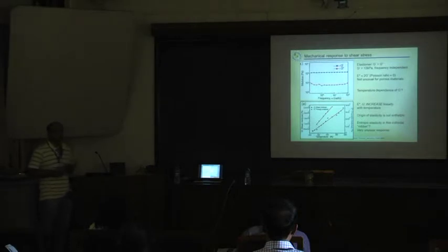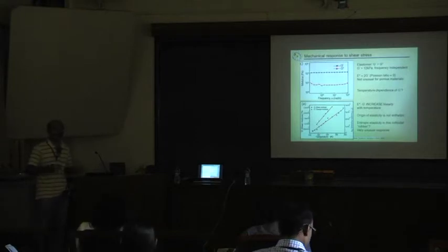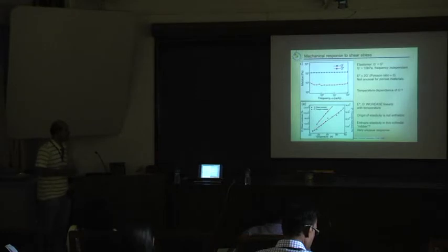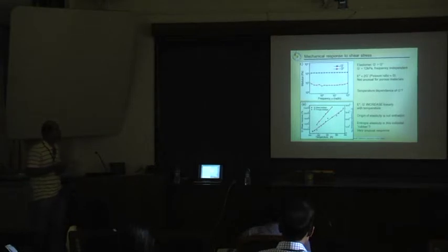Now that's very unusual because for most inorganic materials, or if you take a bunch of glassy particles and bond them together, you would expect a decrease in modulus as you go to higher temperatures. What we see is essentially a linear increase with temperature. That suggests that the origin of the elasticity that we are seeing in these materials is probably not enthalpic, and it's probably entropic, like you would see in rubbers and so on.